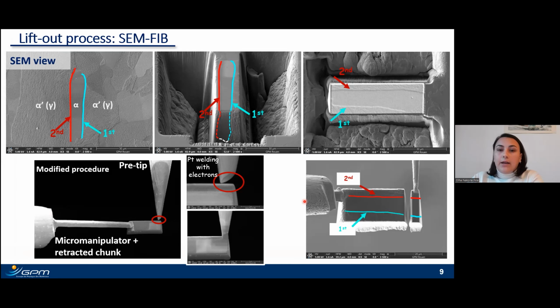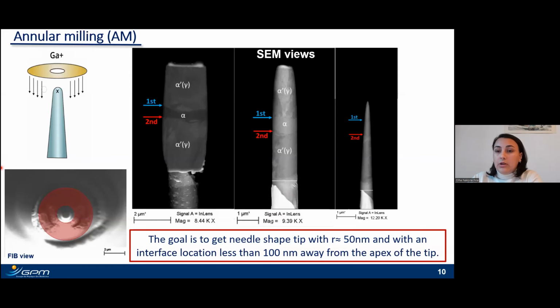Then, to provide a needle shape to this piece of material with a radius of around 50 nanometers, required for an APT specimen, we use the well-known procedure of annular milling. But in our case, we have to control the position of the interface from the tip apex. It is best if it is located less than 100 nanometers from the tip apex. As you can see on the slide, from the contrast on SEM micrographs, we can easily localize the position of the interfaces at the first step of annular milling. But when the tip becomes too thin, we cannot see it anymore.